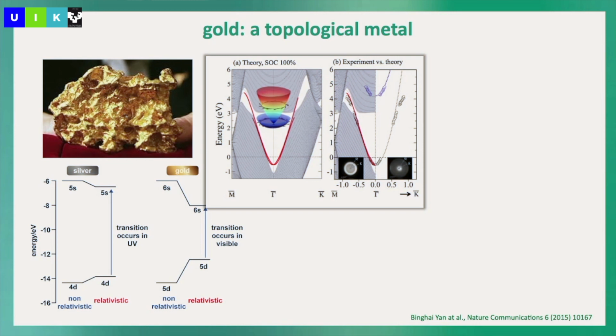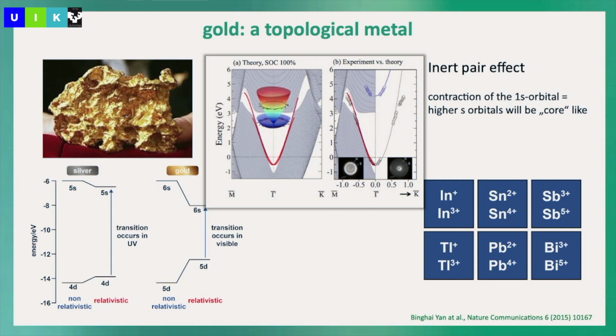And then we looked really for the surface state of gold, so people thought it's a Shockley type of state, and even Shockley was mentioning that if you have 2 bands with different parity crossing, you get a Shockley state, but here it looks a little bit strange if you do the calculation, but it's really a topological surface state in gold, and we really could show, even here's a Fermi energy, with two-photon photoemission spectroscopy that metals like gold can have this very nice surface state, typical for topological material.